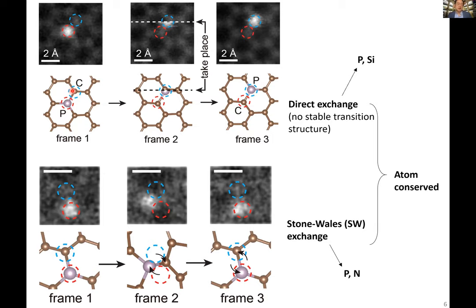This is called the displacement threshold energy, of about 10 to 15 electron volt. And that actually can flip this single bond. So you have a 180 degree carbon-phosphorus bond rotation, and then it just happens. So this is called a direct exchange. And we not only can do it for phosphorus, but we can also do it for silicon dopant.